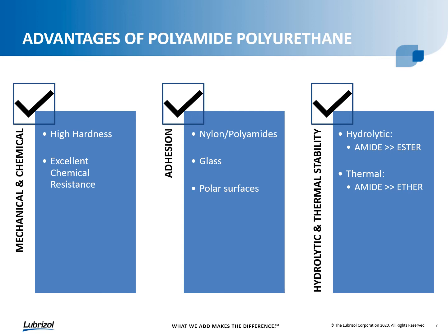Polyurethanes are typically used in your higher performance, more demanding applications because of the properties they provide. And what we see with the polyamide polyurethane is an even higher level of performance over your standard polyester, polyether type materials. When we look at things like mechanical and chemical properties, we see that the polyamide provides very high levels of hardness and scratch resistance, as well as excellent chemical resistance properties, excellent water resistance. And then PUDs generally have pretty good adhesion to a variety of different substrates, but we find the polyamide provides some enhanced adhesion to sometimes more difficult to adhere to surfaces, things like nylon and other polyamides, as well as